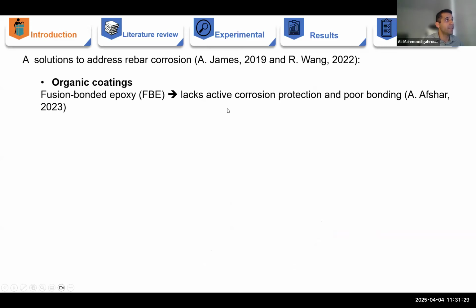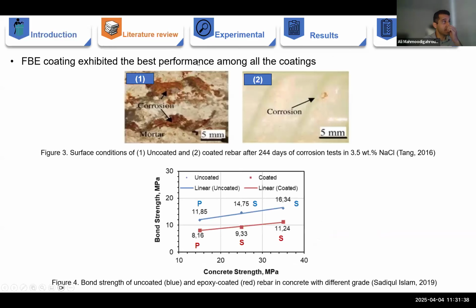Organic coating provides a solution for this issue. However, they lack active corrosion protection and have poor bonding. Here is an example of using organic coatings for rebar. Picture number 1 is uncoated rebar embedded in concrete after 244 days of corrosion test, exposure to a harsh environment. And as you see, there are a lot of corrosion products on the surface. However, for picture number 2, which is coated rebar, the extent of corrosion products is substantially lower, yet we have some tiny spots of corrosion on the surface,